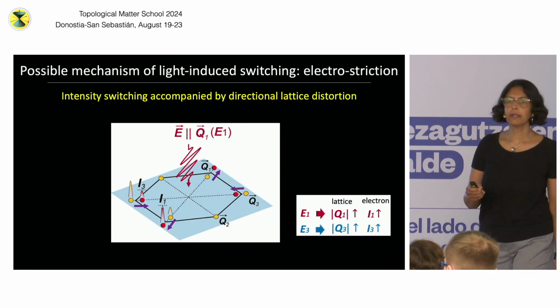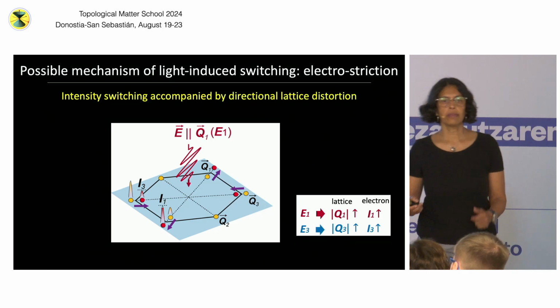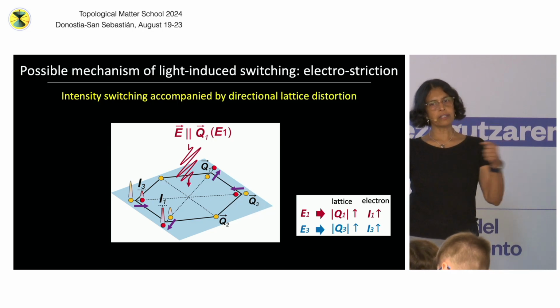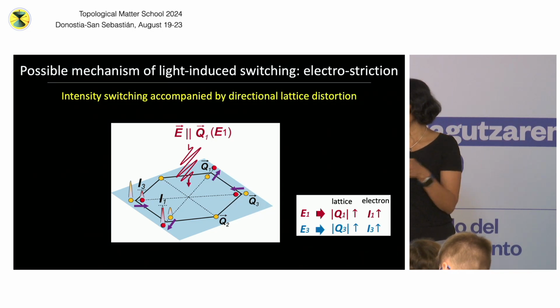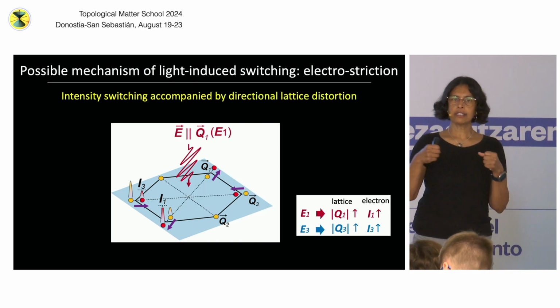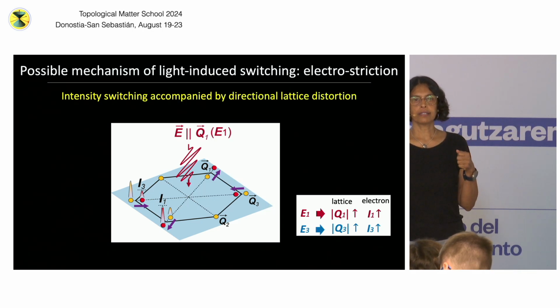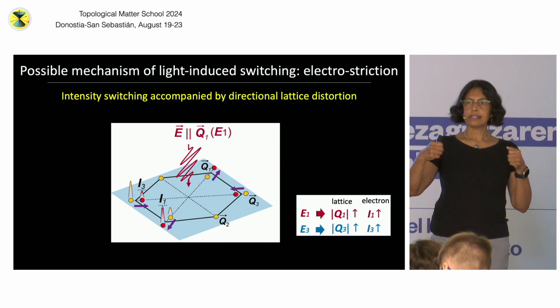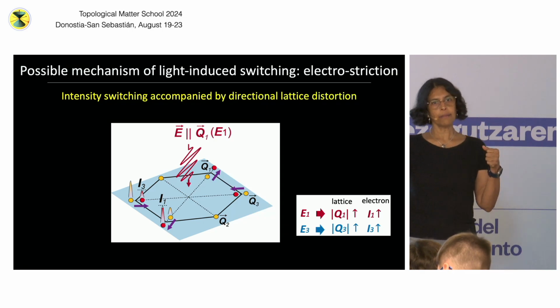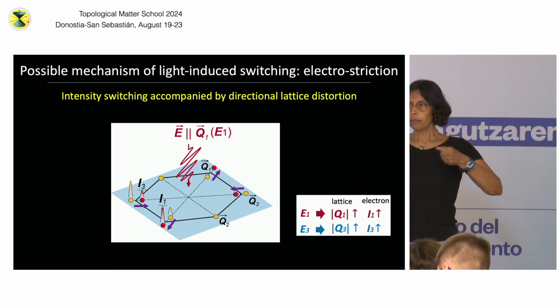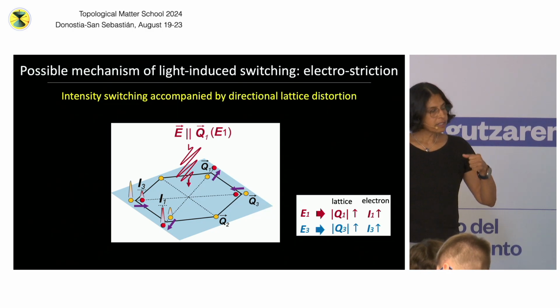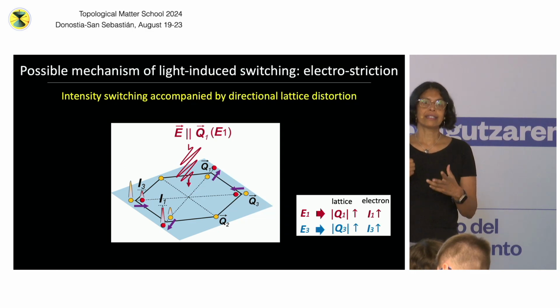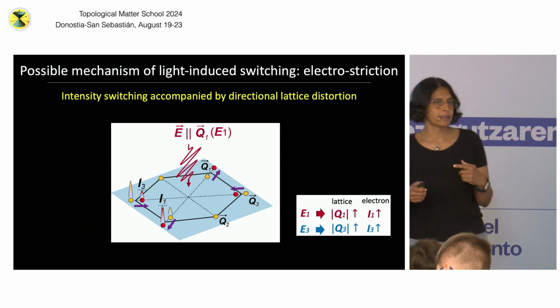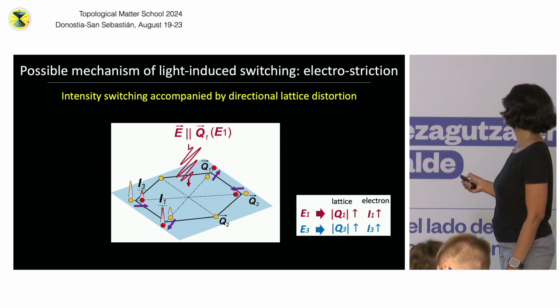So one possible answer is that the light, with the electric field along a direction, is exciting phonons in that direction, and perhaps the system is finding a new equilibrium phase where the atoms are distorted. I told you CDWs are associated with lattice distortion. So perhaps there's a new phase where the atoms are distorted slightly more, and because the distortion is higher, the charge density wave is more intense. That's one possible explanation. That would be something like electrostriction.